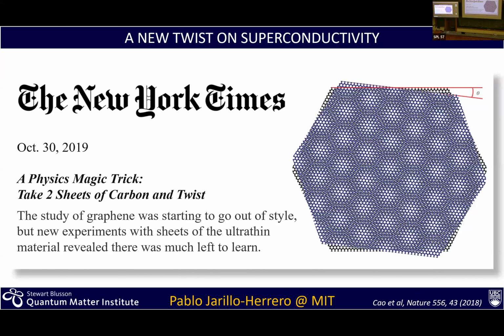Before we saw a Time magazine cover that was about high Tcs, the next big surprise came about twisted bilayer graphene, and here now made the New York Times. And what you're seeing here is a structure built of 2 monolayer graphene layers. These 2 monolayer graphene layers have been stacked on top of each other with a small twist angle. You can see here the misalignment at this particular angle. And as you do that, you see a pattern that emerges from the overlap of the 2 structures, and this is what is called a moiré pattern.